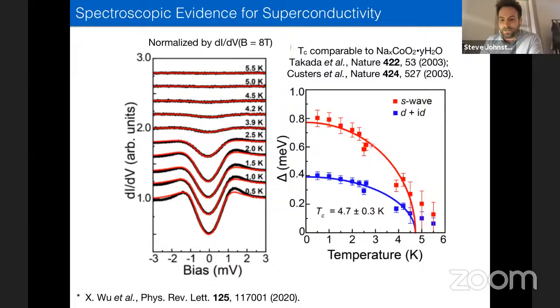The missing data here is coming from some vibration in the system apparently at this temperature, so they couldn't get reliable data there. But we pretty reliably get a temperature of about 4.7 Kelvin. And you can sort of see here at the 4.5 Kelvin data, the beginning of a suppression of zero bias voltage here. So you can kind of see by eye the beginning of the formation of the gap at that temperature.